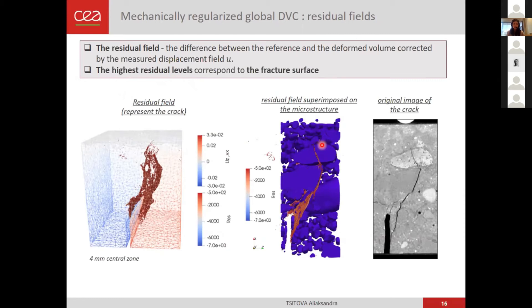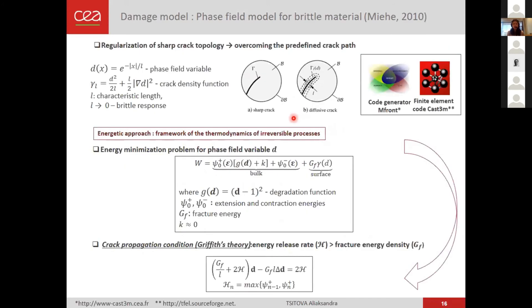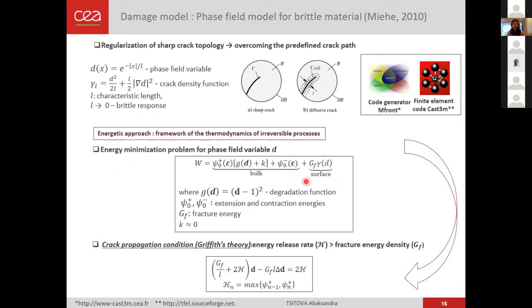The point of the DVC technique was to measure displacement fields to use as experimental boundary conditions, then move on to finite element simulations of fracture propagation. We use a phase field model for brittle material, which is based on the principle of a diffuse damage zone. The crack is represented as a diffusive damage zone where the damage variable varies continuously from the damaged state to the intact state over a length defined by the characteristic length parameter. As this parameter decreases, we approach brittle response. The model is formulated in a thermodynamic framework with a split of energy into positive and negative components, and the degradation of stiffness is modeled with a degradation function associated solely to the positive energy.